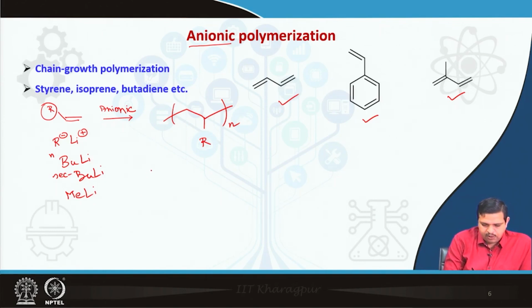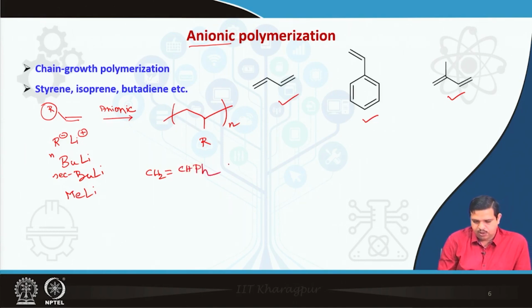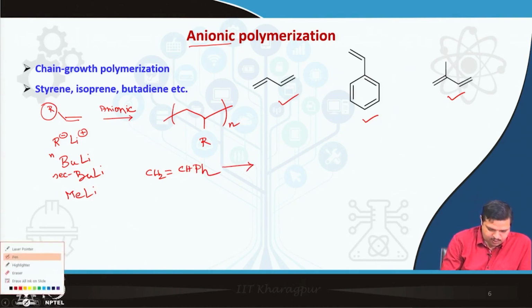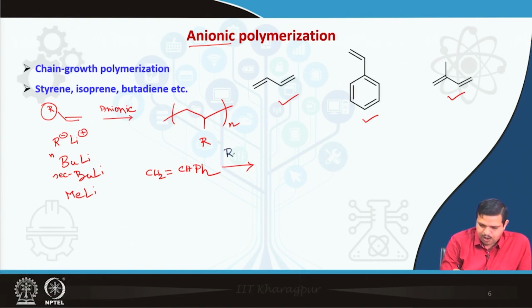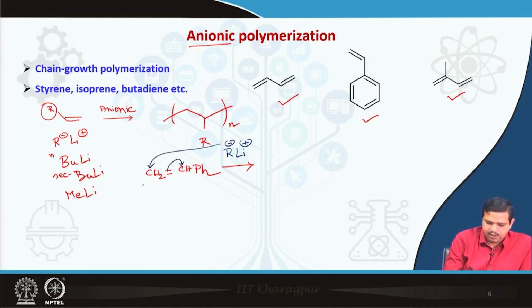If we take styrene molecules where R is equal to Ph here, that is the phenyl, and you take the RLi, maybe butyl lithium, sec-butyl lithium, this one will attack here because this position is less sterically hindered.